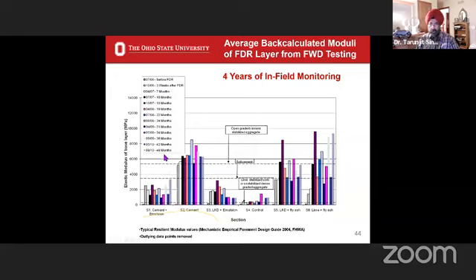Although over the long term, our observation is that in the short term, the LKD and fly ash seem to perform better. But over the longer term, the lime and fly ash section's strength, I should say not strength, stiffness development, performs better. We have done strength tests, but for asphalt pavements, as you know, stiffness is the governing factor for rutting. That is how performance failure will happen in the wearing surface. So we were not as concerned about strength as much as stiffness, because even before the structural failure of the pavement would happen, the rutting would become so much that the pavement would go out of performance and would need some intervention.